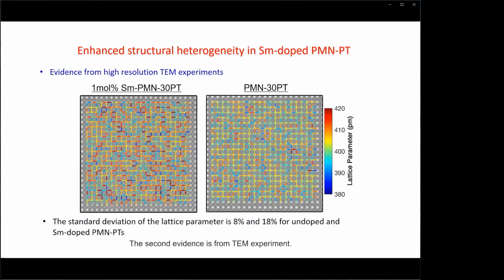The second evidence is from TEM experiment. Here, the colors of the lights represent the lattice parameter. The standard deviation of the lattice parameter is 8% for undoped PMN-PT, while it is 18% for samarium doped one, which indicates that the local structure is more heterogeneous in samarium doped PMN-PT when compared to the undoped PMN-PT.